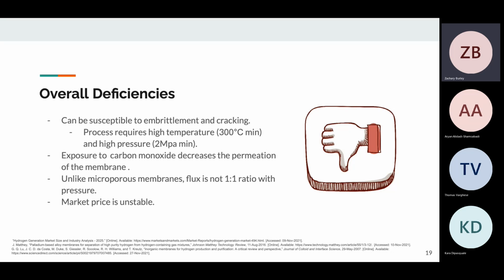This increased temperature is used to combat another main deficiency, which is to avoid embrittlement and cracking. When used in this application, having the membrane operate at a temperature below 300 degrees Celsius will increase this risk and will result in the lifespan of the membrane, which can normally last for a period of 5 years or more, to be reduced.